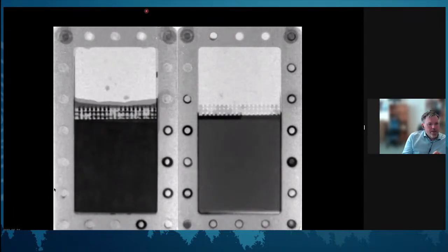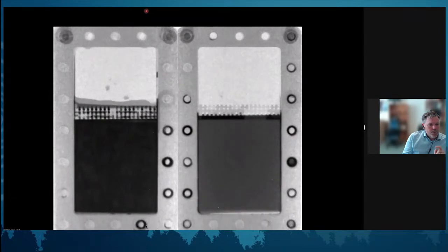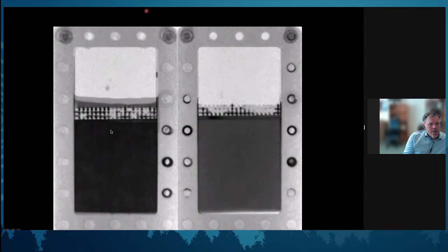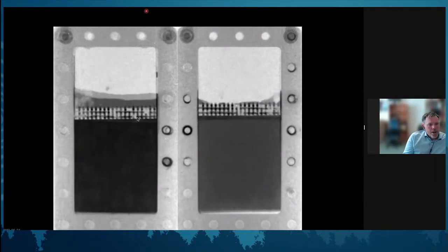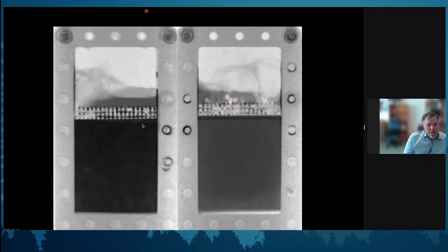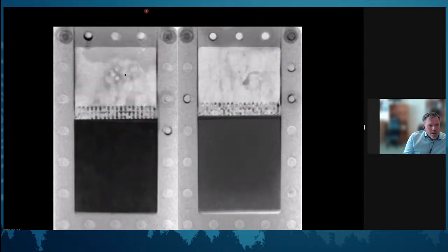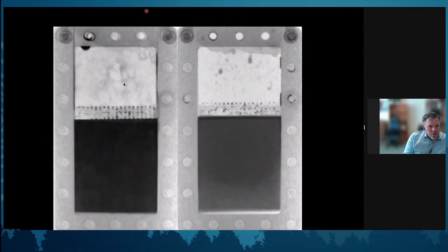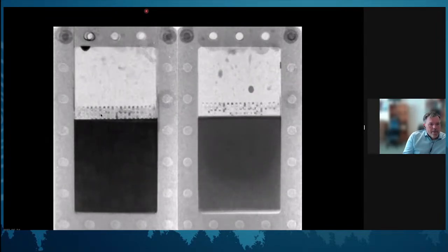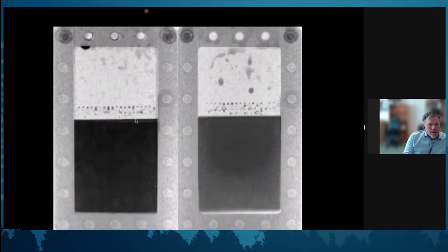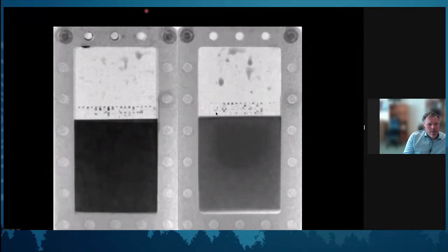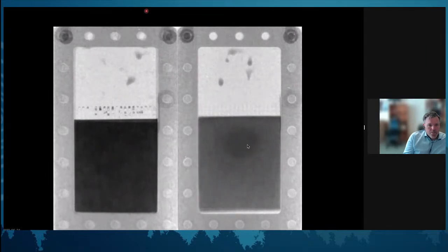And we can see that we are heating it up. We can see that water is disappearing from the holes. We can also see that something is starting to happen inside. And you can see that it's boiling here even. So all water has to go out through the top. This is then this placeholder for the system. We can see that the right one now seems to, something happens, there's a spot here, and what happens is that it dries.